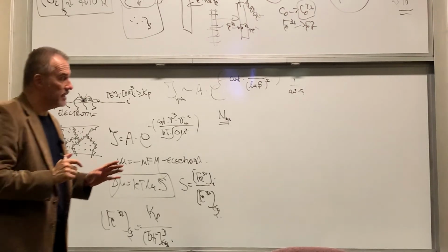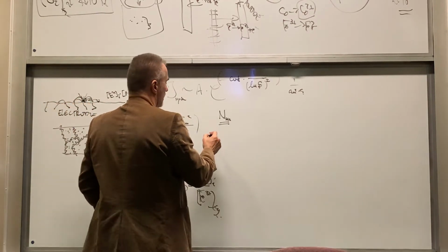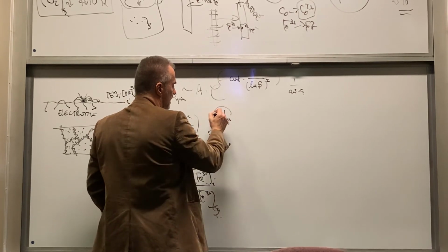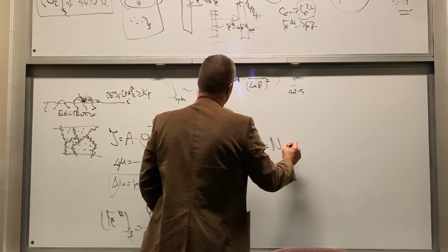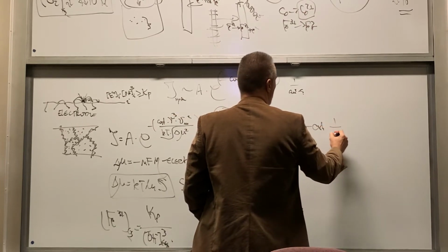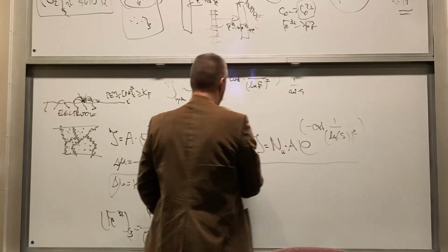Then I can say that the incorporation rate, and I'm going to call it R hydroxide, is proportional to the average size of the incorporated nuclei times the nucleation rate, which is basically m times A, the nucleation rate constant, e to the minus some constant, 1 over ln S to the power 2, right?